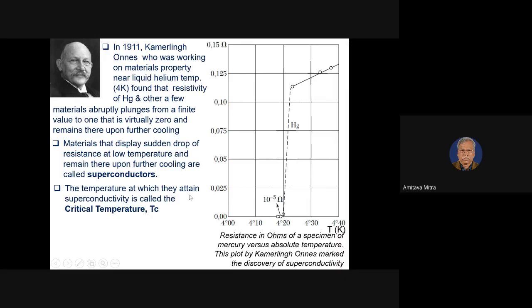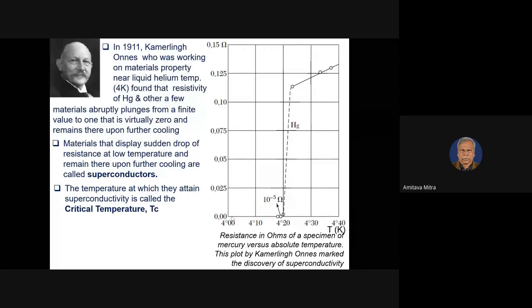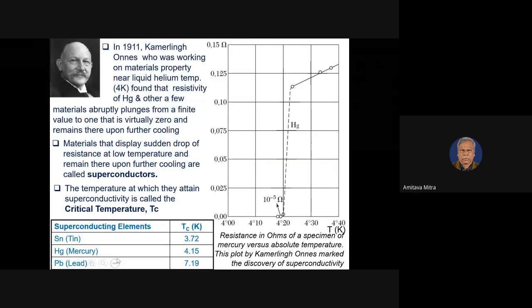To attain the superconducting state, you should not confuse this Tc with magnetic materials, where many times you will find it is the Curie temperature. But whenever you come to superconductivity, it is termed the critical temperature, Tc. Subsequently, he studied various other elements, and he found that tin and lead also show similar behavior. The Tc for mercury is 4.15 K, tin is 3.72 K, and lead is 7.19 K.